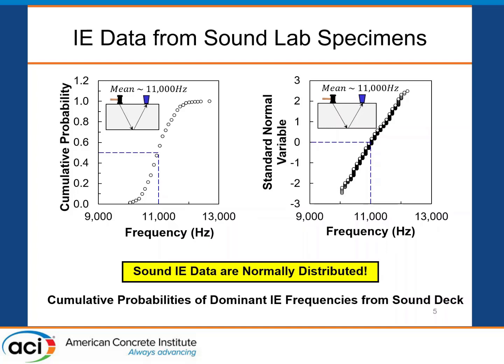It's not actually a log scale, but you can do a coordinate transformation on a regular Cartesian scale to produce the same effect as log paper. When you plot a normally distributed variable on this transformed vertical axis, it appears as a straight line. What's easier to deal with — an S-curve or a straight line? A straight line. And there are well-established statistical approaches for working with straight lines. So all the impact echo plots going forward will use this transform: a straight line just means normally distributed.